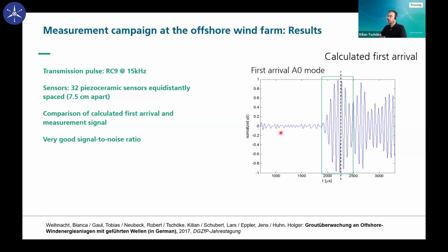This is a real measurement signal from the offshore measurements. We have the calculated first arrival. So this is the point where we approximately assume that the first wave package will arrive. We got this information out of the dispersion curves, and here you can see in perfect agreement the arrival of the so-called A0 mode, which is in total agreement with the calculated theoretical value.